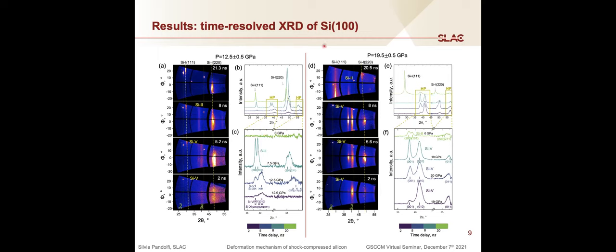Personally, I think the most interesting time series is actually the one at higher pressure, also because it seems that we're crystallizing much more of the high pressure phase, because the signal is much more intense. So it's actually giving us a way to perform a more detailed and quantitative analysis. And in this case, we do see the crystallization of Si-V phase at 19.5 gigapascal. And as we observe at different time delays, we see that the silicon 2 peaks grow.